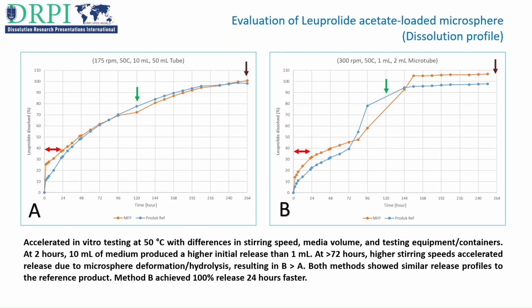Accelerated in vitro testing was carried out under two different conditions: varying agitation speed, medium volume, and apparatus. The effect of medium volume was observed at the 2-hour point. In 10 milliliters medium with lower agitation speed, initial drug release was higher compared to 1 milliliter medium. The effect of agitation speed was observed after 72 hours when more than 50% of leuprolide acetate had been released and microspheres had undergone deformation and hydrolysis. Higher agitation increased microsphere interactions, resulting in faster release under the second condition. Both in vitro methods produced similar release profiles between the final product and the reference product, but the second method achieved 100% release about 24 hours earlier.